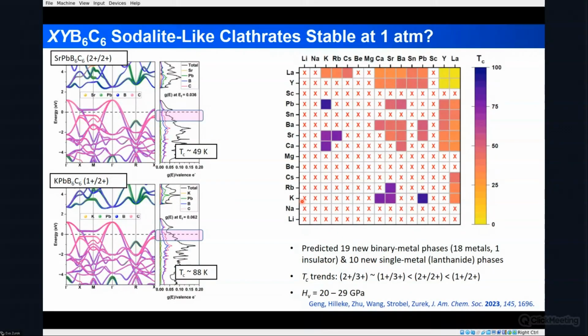So we performed, again, a high throughput type search. The X's denote compounds that are not dynamically stable at 1 atmosphere. And then the other blocks are showing you the predicted TCs for other binary boron-carbide type systems. And what we note is that the B6C6, if you had two trivalent elements within it, this would be isoelectronic to carbon, to diamond. And so the Fermi level would fall right here, and you get an insulator, which is not going to be superconducting. And this is the reason why the yttrium and lanthanum versions of this compound are predicted to be insulating with 0 TC.